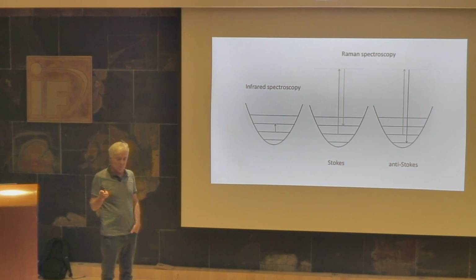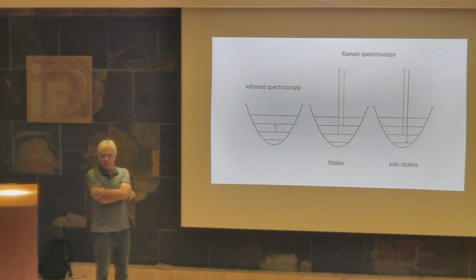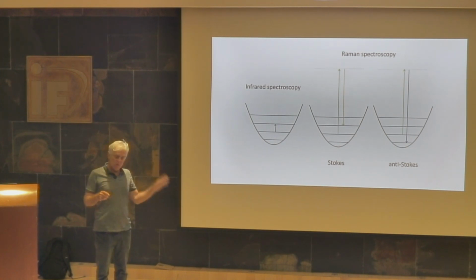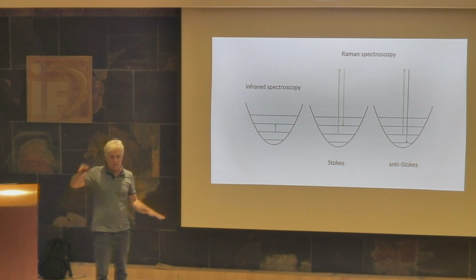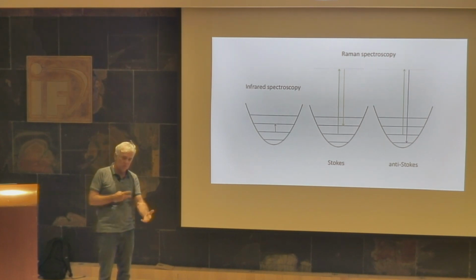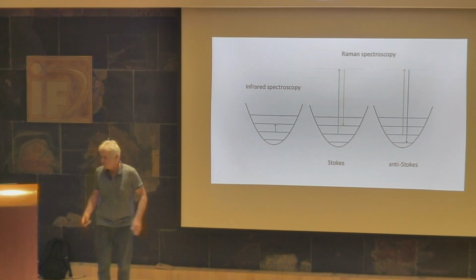Then in some situations, there is what we call the exclusion principle. If the system has inversion symmetry, infrared is an odd process and Raman is an even process. They cannot coexist. Peaks that appear in infrared do not appear in Raman. But if you don't have inversion symmetry, it can happen that one peak appears in both infrared and Raman. By comparing Raman and infrared, we can get information about symmetry. Because the selection rules are different, different phonons are involved in infrared and Raman spectroscopy.